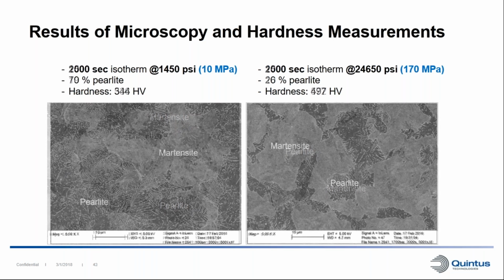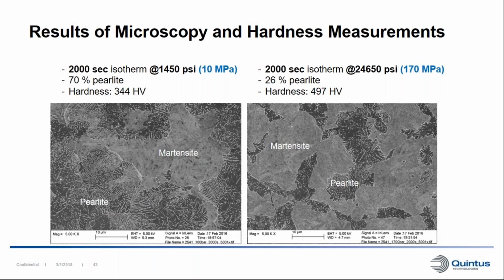When we moved further into the transformation, at 2000 seconds of isothermal time, we could see that when we processed with the low pressure, we got 70% pearlite. And when we processed the same thermal cycle with the high pressure, we only got 26% pearlite. So quite a big difference there. Looking at the hardness as well, it shows the same results: 344 Vickers versus 497 Vickers.